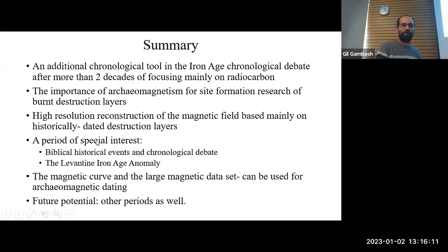Now, this period that I talked about is very interesting also because of the biblical campaigns and all the chronology debate. And also, what I didn't talk about so much, during this period the magnetic field was very, very strange. It's what we call the Levantine Iron Age anomaly. As I showed, more than two times stronger than today's field, with these peaks going up and down. This is very, very interesting for geophysicists. As I said before, geophysicists have no other method to reconstruct at this resolution. Sometimes we can show the difference between the 604 and 586 destruction. For changes at such a resolution, there's no other way to do it. So there are now geophysicists working on this database to try and better understand the magnetic field of the Earth.